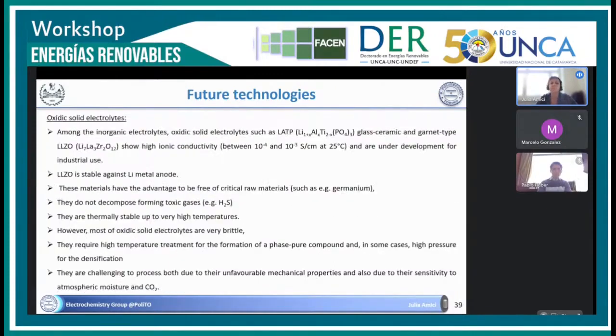For the oxidic solid electrolytes, the ones that are actually considered are LATP, or for example, garnet type, glass ceramic, garnet type like LLZO. This one has really high lithium conductivity, even at room temperature. LLZO is stable against lithium metal. They don't contain critical raw materials, for example. They do not decompose, forming toxic gases. They are thermally stable, of course.